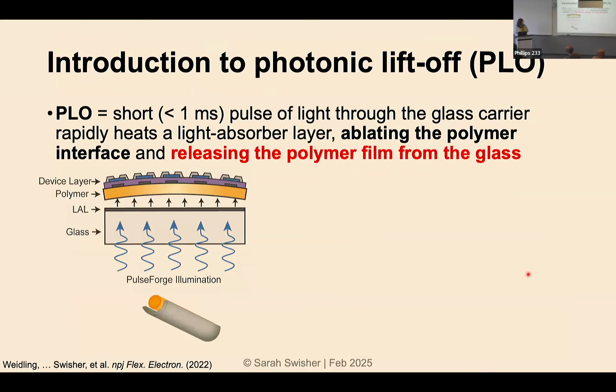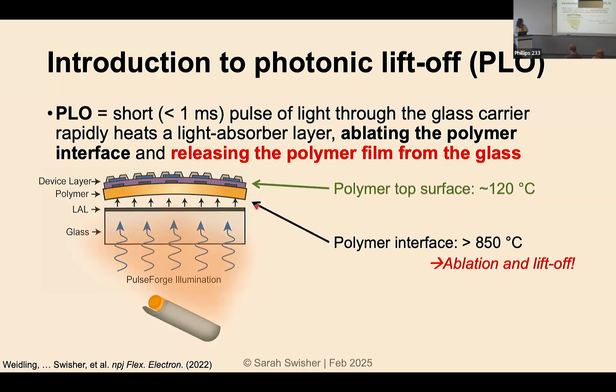And so the PLO process uses a higher voltage and a shorter pulse, but it's otherwise fundamentally the same as the curing process. So we illuminate the device from the back. The light goes through the glass substrate, gets absorbed in our metal light absorber layer, and it actually ablates the polyimide at this interface here without heating the device layer up here. We looked at different thicknesses of this polyimide layer, and for 10 microns or so, that's enough to really keep your devices cool, while this gets to about 850 degrees, which is enough to ablate the polymer at the interface and allow it to lift off.